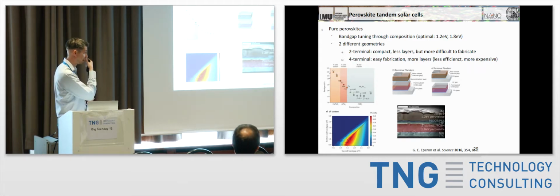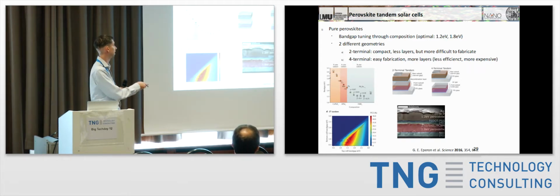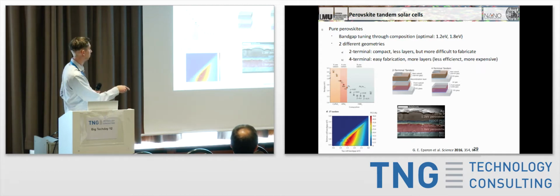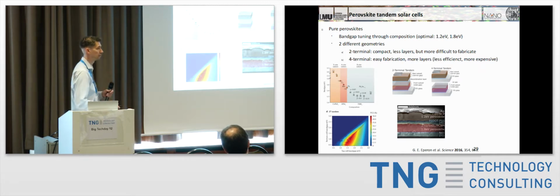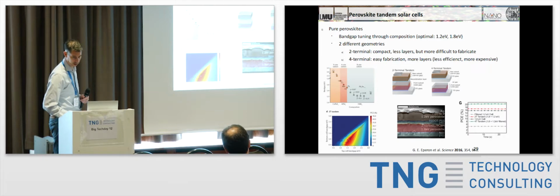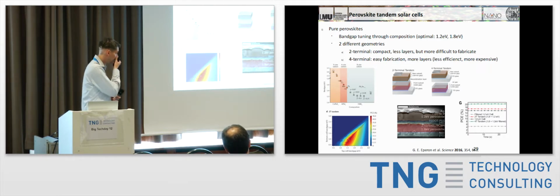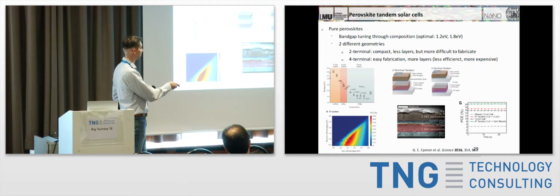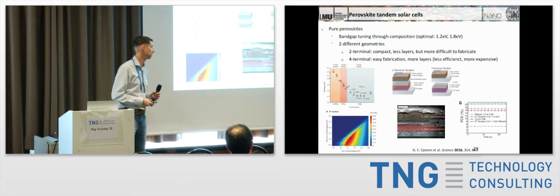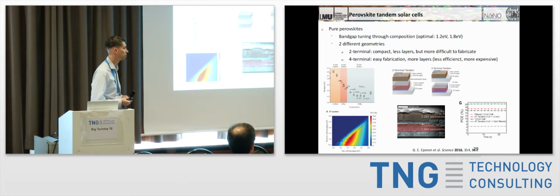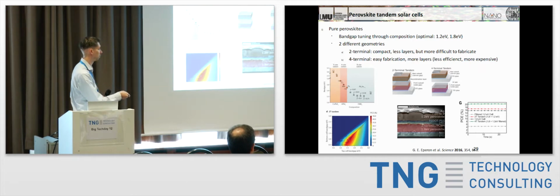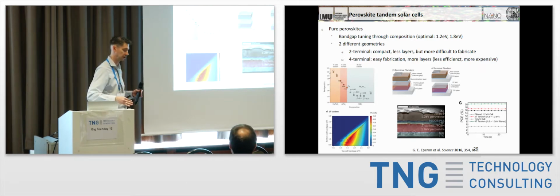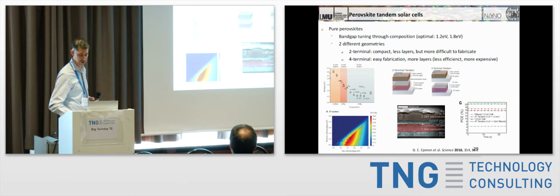And so this is again another cross-section of one of these tandem perovskite solar cells, with the top layer absorbing at 1.2, the bottom at 1.8, and you can again see here this scale bar is 500 nanometers, so this entire thing is very, very thin. And efficiencies they showed there are still below what you can actually get in single junction perovskite, so you can see that while theoretically it's quite easy to do, it's very, very difficult to actually match all of these energies to get all of these layers nicely consistent and sitting on top of each other. So it's definitely something that people are working on right now.